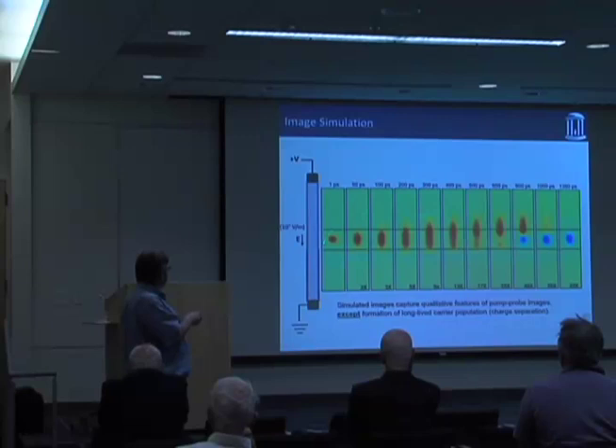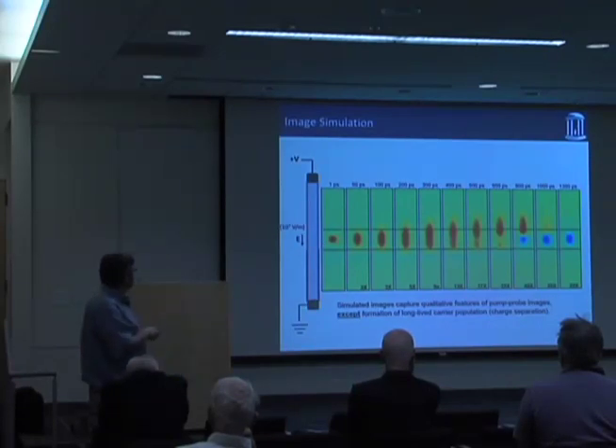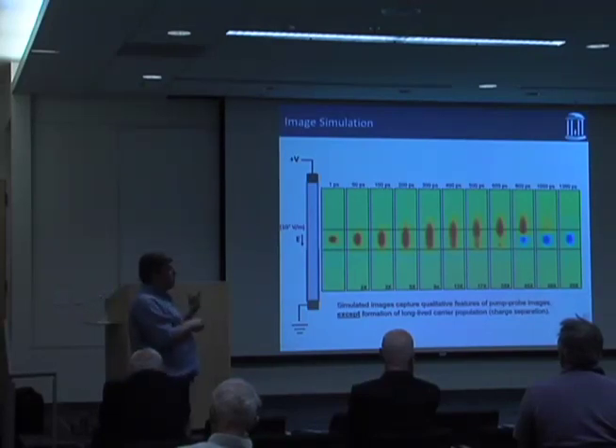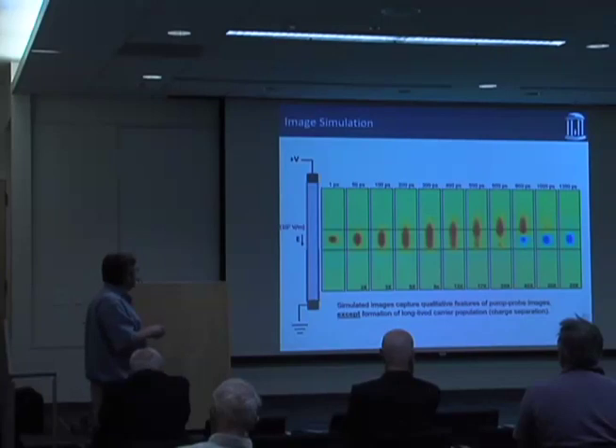And so the vast majority of what we're seeing here is not necessarily charge separation. In fact, we think from the simulations that probably only about 1% of the carriers actually undergo charge separation. But a lot of the asymmetry has to do with the fact that you have these different recombination velocities across the junction. Nevertheless, we do think that we are seeing this charge separation at long times.